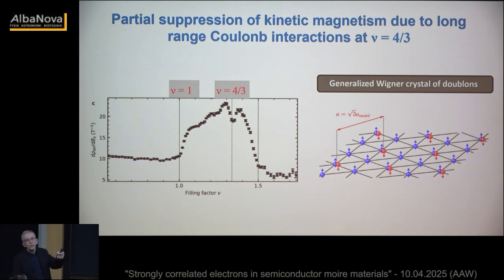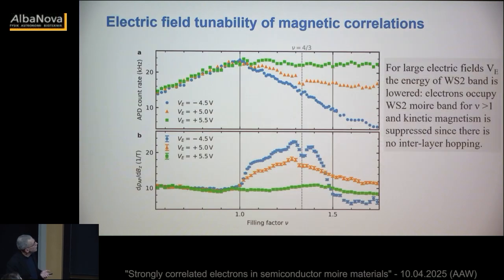We observe a micron-sized spot, but the lattice length scales are not identical within this spot. All right, and we can control the magnetic correlations electrically. This one's also lined up. And this, again, shows you that by applying a large electric field and hybridizing the 2 conduction bands, we can actually kill the magnetic correlations.